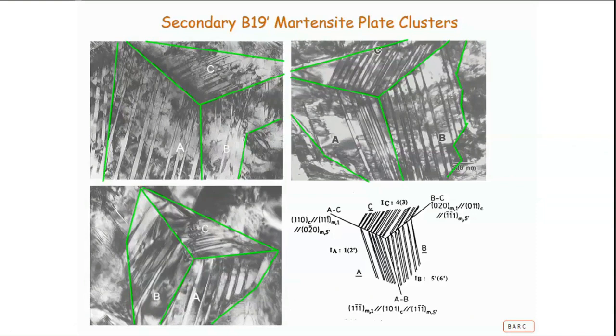Certain things are very close to scattering because they're closer to the Bragg condition. They scatter more, and some scatter less. And so the contrast which you get, the dark and light, is that the one that scatters more appears darker, and the one that scatters less appears brighter because everything comes in through the aperture. And you can see this dark and light contrast, and that's what you're seeing. But it helps us to see this because you can see that there are two different orientations within this. So this is an interesting feature of martensite also.